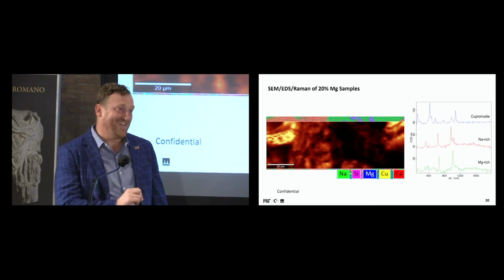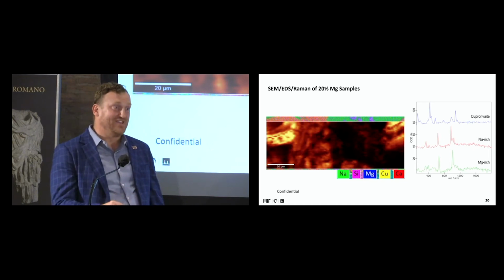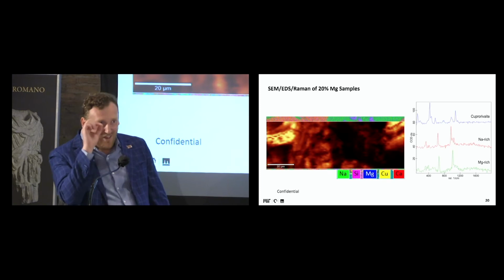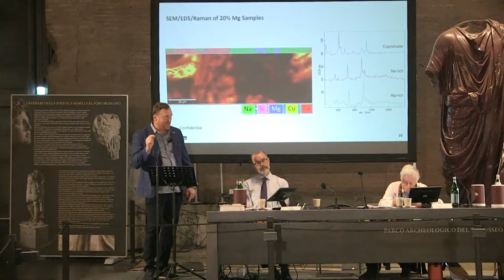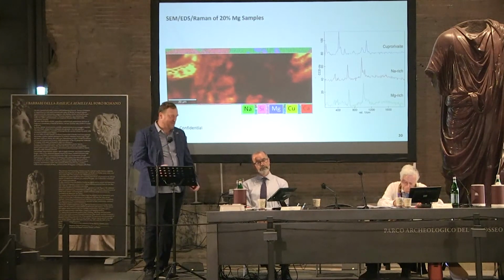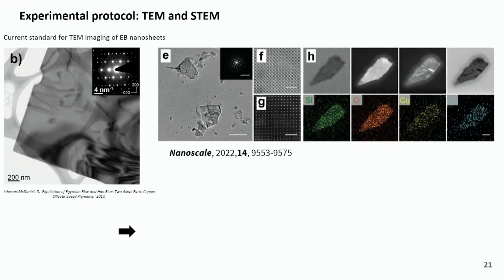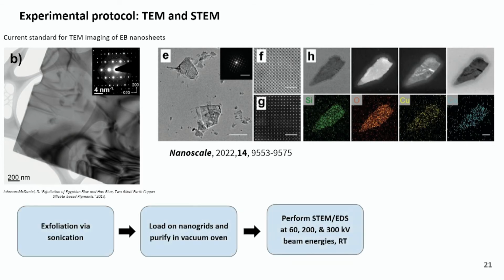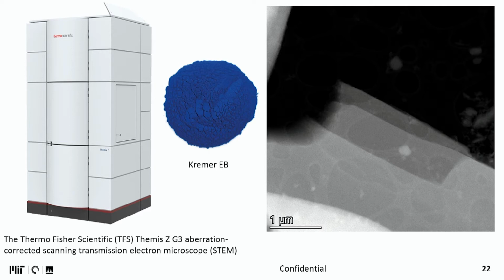And it would be nice now to see if magnesium, perhaps even in small numbers, maybe atoms go and substitute in the structure. And so this is what we did. We tried to do atomic resolution scanning transmission electron microscopy, which we are blessed to have at MIT.nano at MIT. And these are the first results on Egyptian blue, on the sheets that were exfoliated from Egyptian blue. And this is what we got.